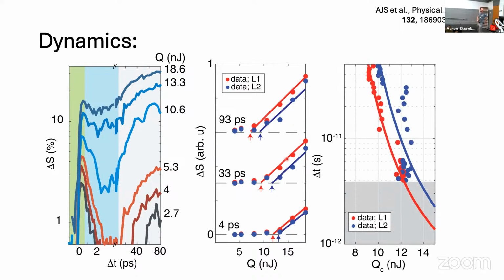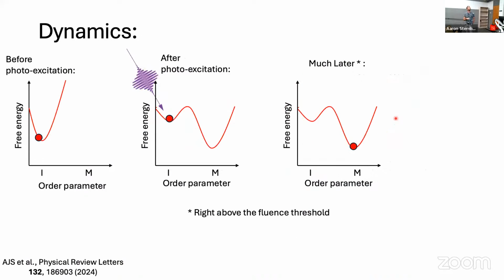So summarizing this data, all in this plot, what you can see is that there is a time-dependent fluence threshold of this system. And at a neighboring location, the system essentially takes a longer time to reach some probability of evolving into a metallic state.